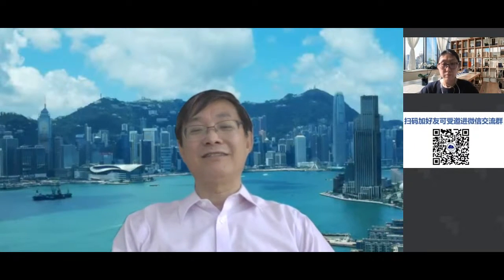You can see we can start from so-called high entropy alloy, by adding some element like silicon or other, that can facilitate the formation of the glass phase, then we can obtain another material. So I think what we have opened is the possibility to do all this kind of material. But to facilitate it, it's better to choose a material which may not have a very strong glass formability. Because for the people working on metallic glass, we always try to have a high glass formability material. But I think we need to change the mind.